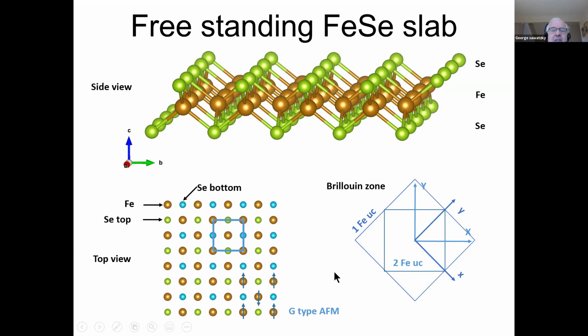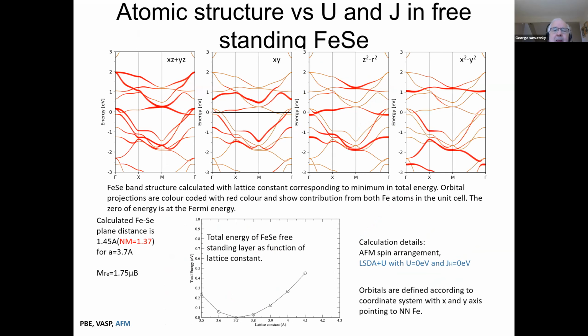Okay, so let's go and have a look at this. So this shows you the density functional calculation just in an LSDA calculation. And it's relaxed. And if you do LSDA, you actually find, and this is G-type, this is not stripy, this is G-type. Now, for many of these things, as far as lattice constants versus magnetism is concerned, the magnetic order really doesn't matter so much. What matters is whether or not you have a local moment.